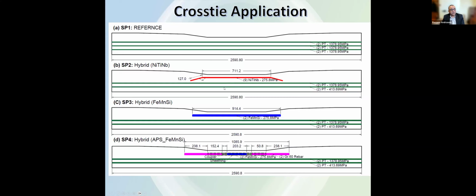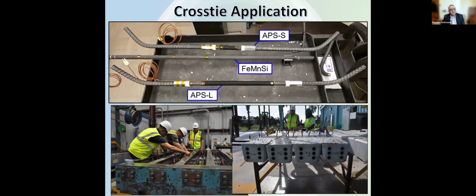And then we could also add just localized pre-stressing using SMA bars just at the center region. We tried different configurations. We visited their plant in Florida for a couple of days, and we worked with them on implementing this technology in their ties. And once the concrete was cast and set, they shipped it to us for testing. It was very, very fruitful, an exciting experience we had with Rocla Concrete Tie.